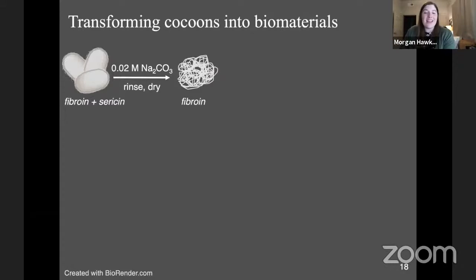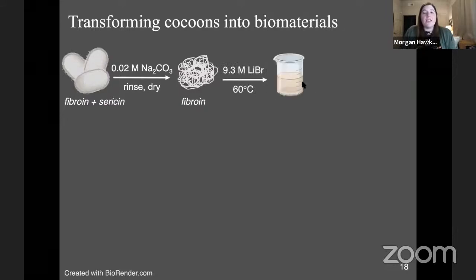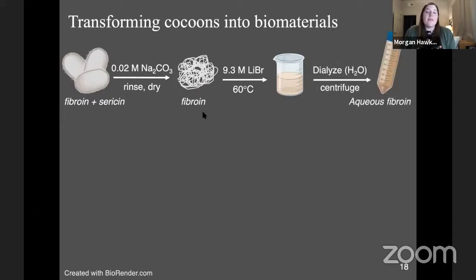And you can think about this as looking like kind of a cotton ball type of material. If you were to pull apart a cotton ball, that's effectively what the fibroin looks like. It's this white, stringy, fibrous material. The fibroin can be dissolved in lithium bromide to yield this concentrated, viscous solution, which can then be dialyzed against distilled water to remove lithium bromide. And the reason why we want to go through this whole process is to obtain this aqueous fibroin solution. And you might be wondering, well, what's the point of having a polymer solution in the aqueous phase? And actually, it opens up a ton of possibilities.